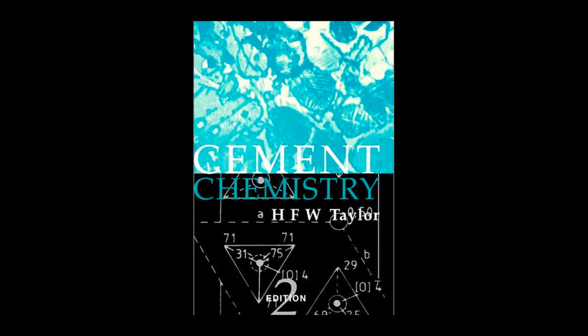Exactly. And at the same time, the solution chemistry theory is at play. Even though the reaction is slowed down, ions, specifically calcium and hydroxide ions, continue to dissolve into the pore solution. They just build up very, very slowly during this induction period. And then something triggers the end of the pause. The pause terminates when these ions reach a critical threshold of supersaturation. Once that threshold is hit, it triggers the mass, almost instantaneous precipitation of CSH and CH throughout the available space, and that initiates the dramatically fast acceleratory period.